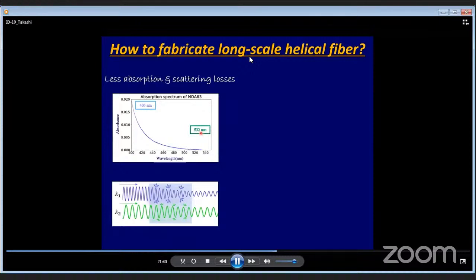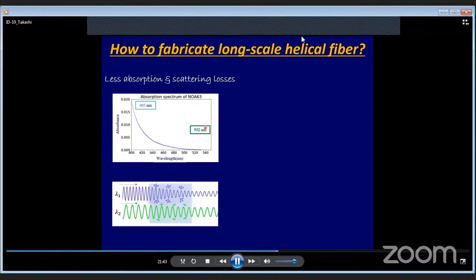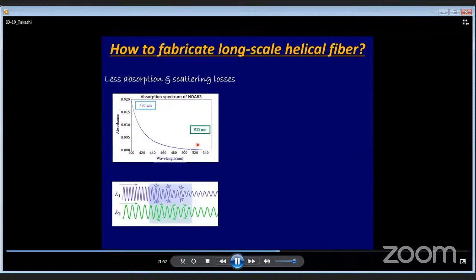In order to reduce absorption loss inside the material, we decided to use 532 nanometer visible light. This wavelength corresponds to the cut-off value of the absorption band of the material itself. We expect significant reduction of the absorption loss inside the material. According to the Rayleigh scattering theory, we also can reduce scattering loss inside the material. Namely, by utilizing the visible light, we can significantly reduce absorption loss and scattering loss as well.